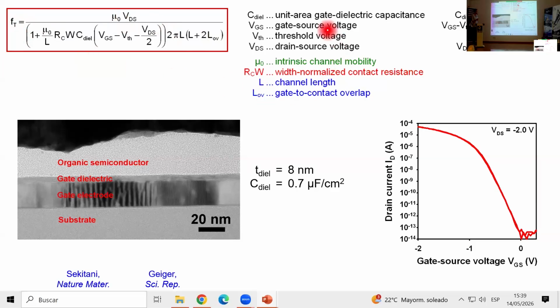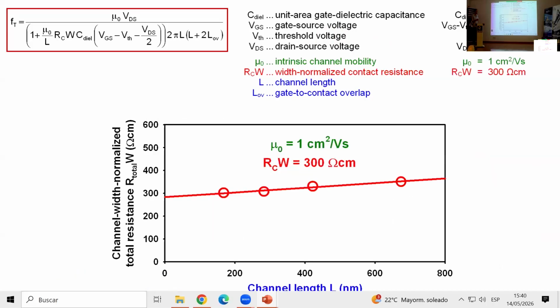Okay, so the transit frequency is going to be dependent on these 8 different parameters here. Again, like in the previous case, I have to make a few assumptions in order to be able to do anything useful with this equation. So I'll choose the same values again for the gate capacitance and the gate source and drain source voltages. And again, I'm going to use a value of 1 centimeter squared per volt second for the intrinsic channel mobility. And this time I'm going to use a value of 300 ohm centimeters for the width normalized contact resistance. And the reason I'm using these two values is that these happen to be the values that we extract by performing the transmission line method analysis on the transistors that I'm going to talk about in 1 minute.